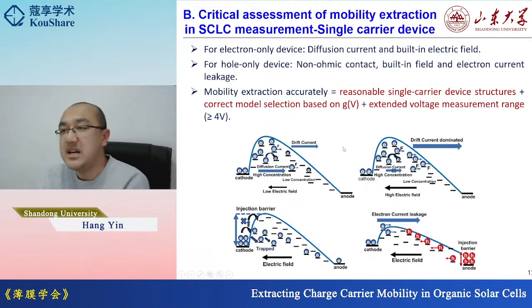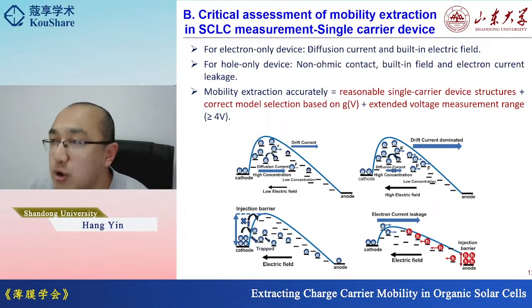So we just differentiated the electron-only and the hole-only devices, and we get the conclusion that we need different requirements for different kinds of single carrier devices. And how to get the relatively accurate mobility value? It equals the reasonable single carrier device structure, plus the correct model selection based on the G value, plus the extended voltage measurement range. Usually, for the current organic solar cells, we have to fit it to voltages larger than 4 volts.